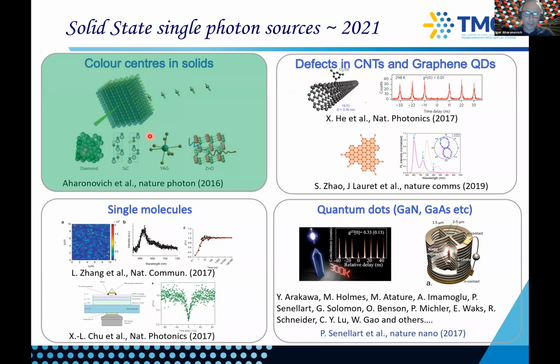And when I mean robust system, I mean, as a first-year graduate student, when you drop your sample on the floor, you can actually pick it up, put it back under your confocal microscope and nothing really will change. So the defects are very deep within the band and protected by the lattice. So it's a very convenient system to work with.